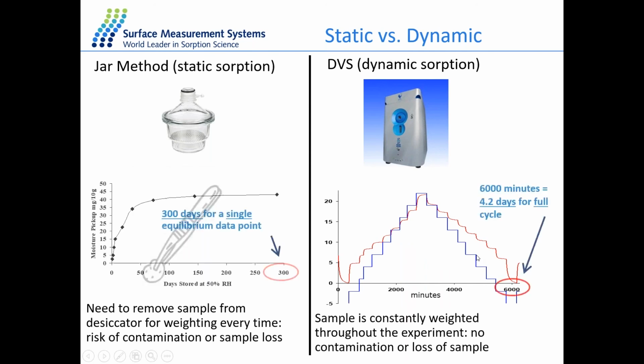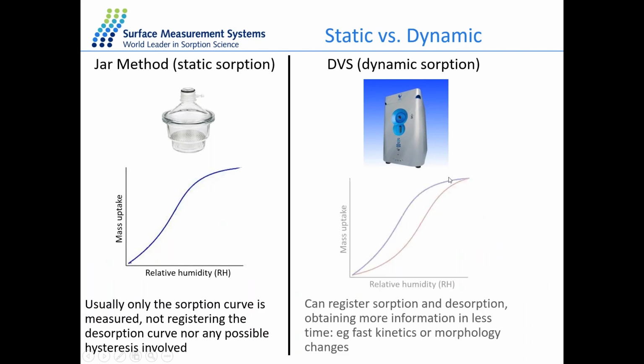And we measure the sample continuously without taking out the sample, so we can get a more accurate result without any contamination or loss of the sample. From the DVS data, we can get both isotherms of sorption and desorption, and the gap between sorption and desorption is called the hysteresis gap, also telling us some information about the system, the material itself.